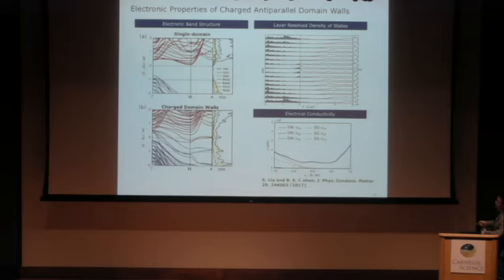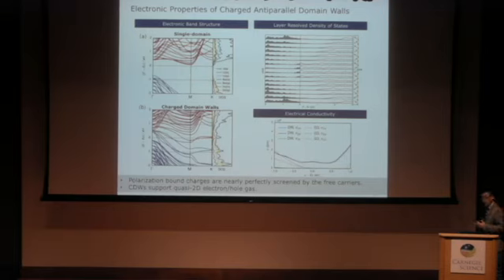As expected, along the domain wall, within the plane of the domain wall, the electrical conductivity has a metallic signature, but perpendicular to the domain wall, that is across the supercell, the conductivity is still very low. So we think many hyperferroelectrics, in this case lithium, beryllium, antimony, are potentially really ideal candidates to study high-density charged domain walls. They may also have potential device applications because of this quasi-two-dimensional electron and hole gas.